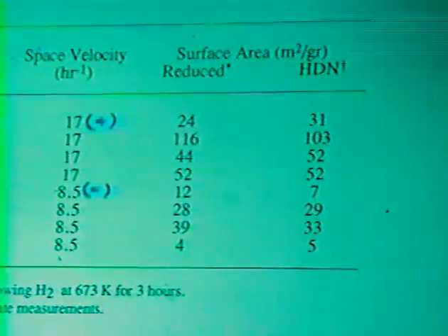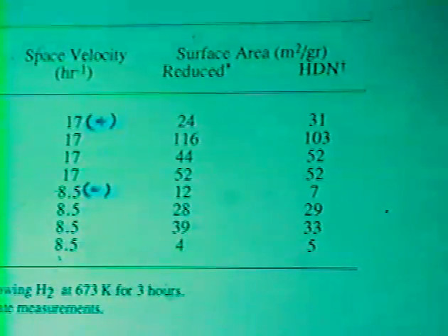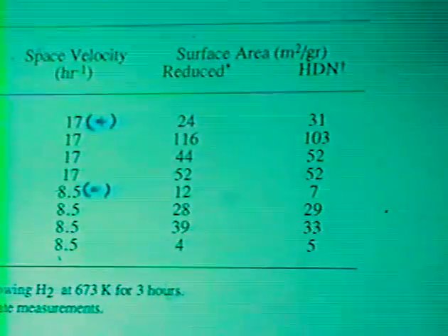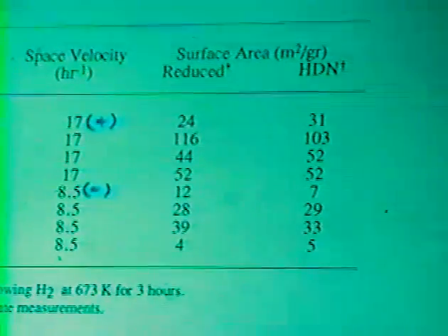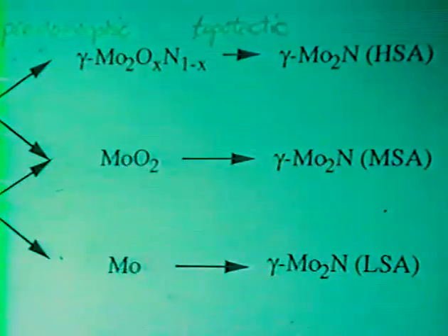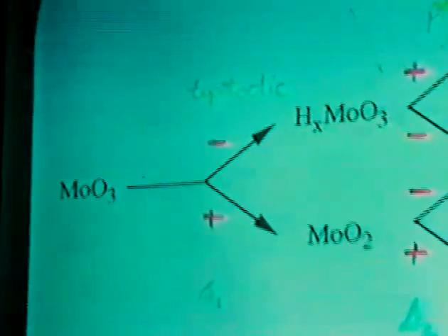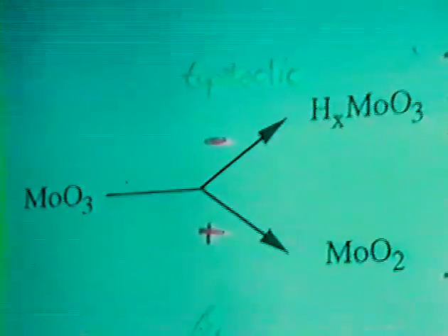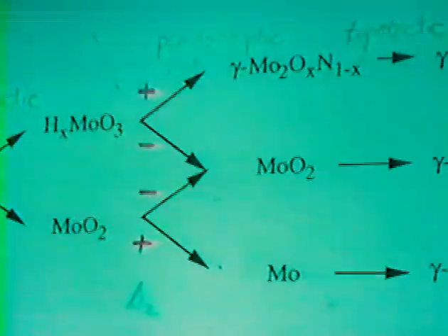recognize that there is a broad variation in the surface area as a consequence of the synthesis parameters that were employed. Please remember that sample number 2 has the highest surface area, 116 square meters per gram. Sample number 8 has the lowest surface area, 4 square meters per gram. Throughout this part of this talk, we will make comparisons between these 2 materials. And let me also mention that we could categorize these materials as being low surface area, medium surface area, or high surface area, and you see the ranges that we use in this particular work.